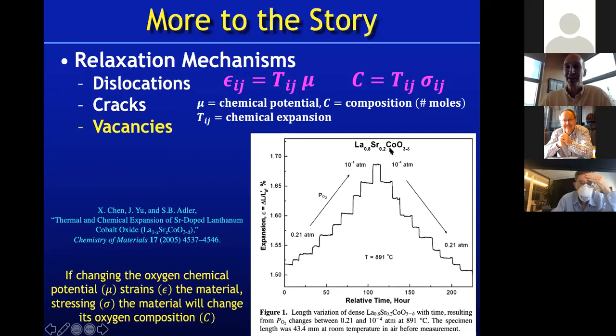magnetically ordered material, lanthanum strontium cobalt oxide. It's a nice perovskite material. From a chemical standpoint, the cobalt in this material is a mixture of 3+ and 4+. 4+ cobalt takes very high oxygen pressures to stabilize. So it's common for this material, if you want to make it O3, not O3 minus delta, to use pressures like 5,000 atmospheres to drive oxygen toward 3 and see the true intrinsic